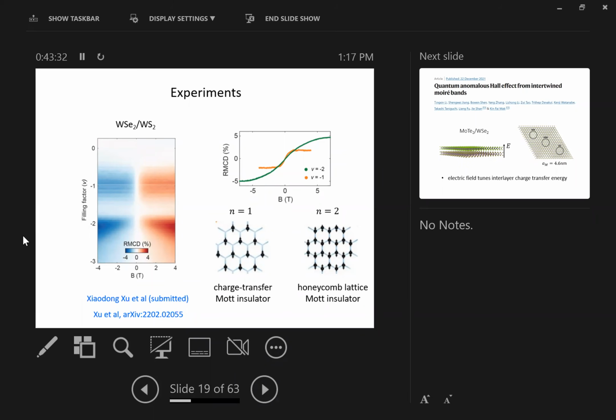On the other hand, if you take into account this charge transfer picture, everything can be explained naturally. There are 2 sites per unit cell, and together they form a honeycomb lattice. So when you are at filling factor 1, the charges all occupy the one sublattice, which has a lower energy. But when you dope it above n equal 1, the doped charge now has no choice. To avoid double occupancy, it has to occupy the second sublattice. So when you dope it all the way to filling factor 2, every site, both sublattices, is occupied.